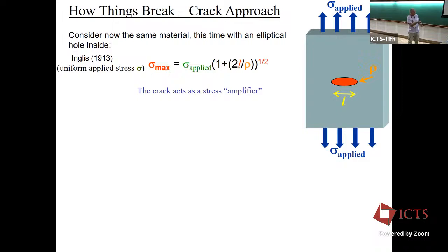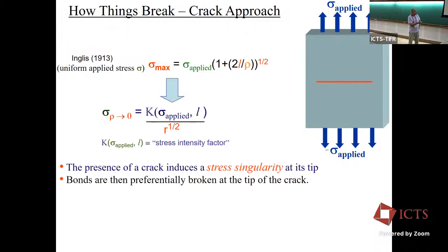Now, what happens though if we start to take this ellipse and squash it? The curvature here gets larger and larger, or the radius of curvature gets smaller and smaller. And so what we find is that if we take the limit of squashing this ellipse to a straight line, the stress at the tips of the crack, this is now a crack, are singular.